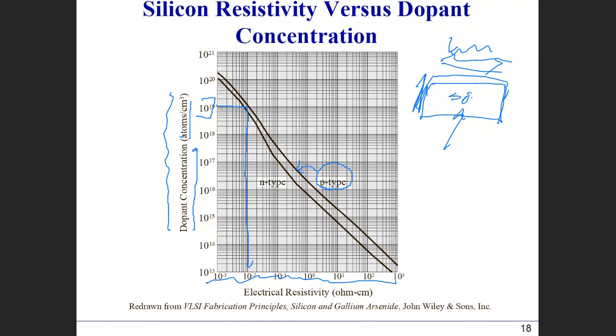10 to the negative 2 ohm centimeter. Okay. Awesome. If you have lower doping, as you can see, a very small amount of atoms, 10 to the 14 atoms per cubic centimeter, the resistance is going to be very high. Something like this. In the silicon case, this kind of graph is very well established. So you can roughly estimate, from the measured resistance of your sample, the doping concentration of the material.